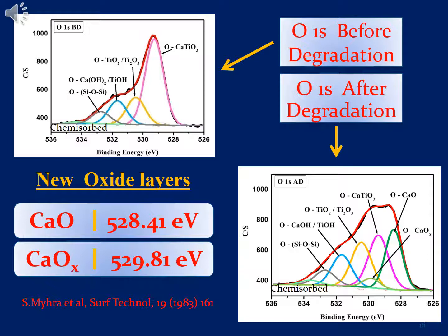Now, my interest is more on what is happening after I expose my material to a prolonged electron beam. What I see immediately from the oxygen peak is that the peak is broadened to accommodate an additional peak at lower binding energies. And when we fit, we realize that we are forming calcium oxide, and consequently we also realize the intensity of the calcium peak is reducing with respect to the titanium to calcium ratio.